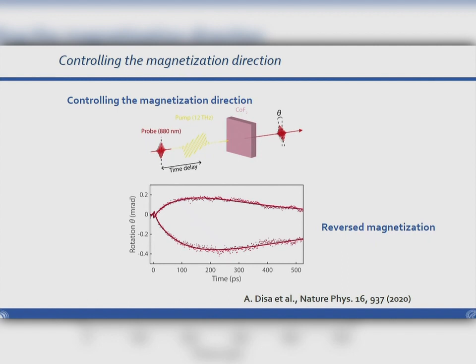So we repeat the measurements now for a 90-degree rotated pump polarization. And now the Faraday rotation goes in the other direction. So we can reverse the magnetization that we induce by this process.